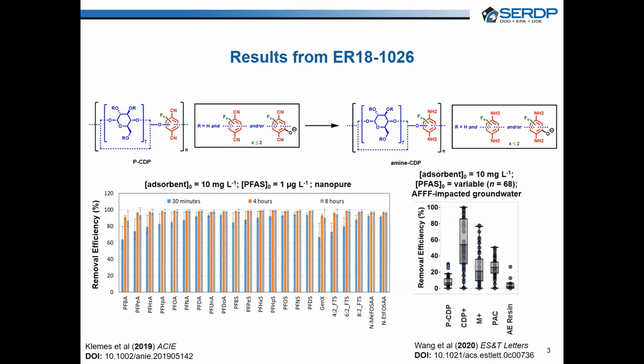On the right of the slide, I'm showing data from another study where we evaluated the performance of 3 cyclodextrin polymers alongside a powdered activated carbon, PAC, and an ion exchange resin, AE resin, for the removal of PFAS from an AFFF contaminated groundwater sample. We measured 68 PFAS in the groundwater sample, and we found that one of the cyclodextrin polymers, which we call CDP plus in this figure, could outperform the conventional adsorbents under these real-world conditions.